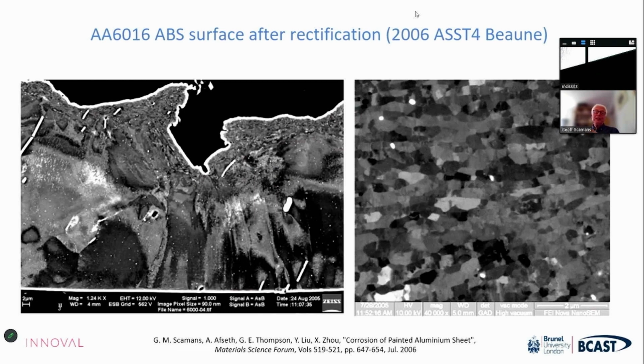You can see just what happens when you take an aluminium 6000 series alloy, in this case 6016 automotive body sheet, and rectify it. You can see the pronounced surface topography produced by the grinding, and you can see the beautiful deformed surface layer sitting above the normal grain structure. And now with higher and improved resolution low kV SEM, you don't have to see these ultra fine grain structures in the TEM anymore. You can actually pick them up in a good SEM, which makes analysis a lot easier.